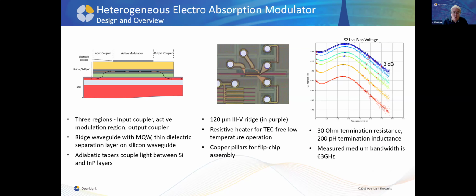The output couplers are important because that allows you to get the low loss as well. And this is basically what we have in the PDK today. It's a 30 ohm termination resistance device with about 63 gigahertz average bandwidth, measured as S21. And it can be designed into a silicon photonics flow that then can be bumped with copper pillars for full flip chip assembly, and doesn't require tight temperature control like a TEC for full band operation.